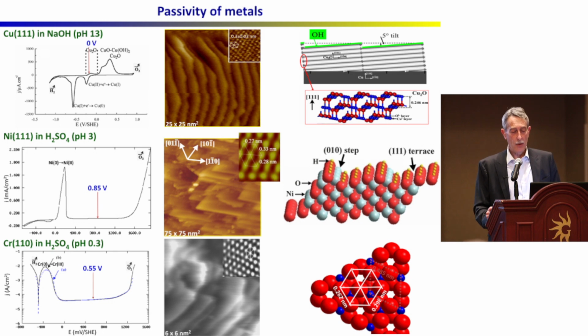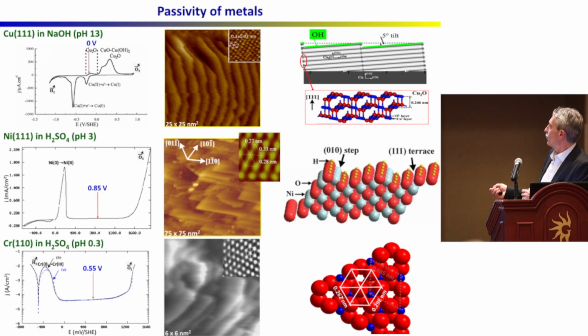Now on nickel, you also have this tilt between the oxide and the metal, and this is producing steps at the surface. So the substrate is there, and that's the model derived from the STM experiment. So you see that even if you have a very smooth nickel surface, it's a 111, so it's the most compact and smooth at the atomic level. However, because of what I've said about the interface and surface energy minimization, at the surface of the oxide you have these terraces and steps, and they are hydroxylated.